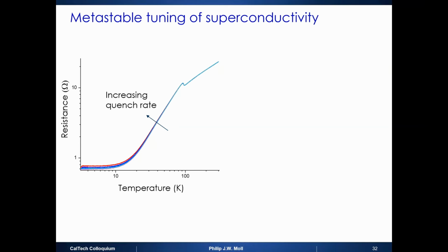So we're now tailoring the pulses. We need to go to even shorter time scales to quench it more brutally, right? But it works. And so then as you warm it up, you see above the charge density wave transition, there's no more memory. That makes sense. You melted it thermally again, so there can't be any residual thing.